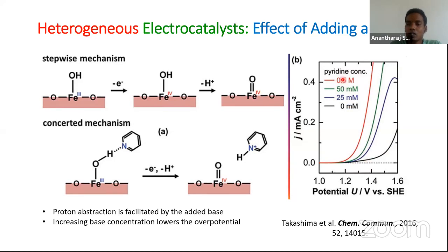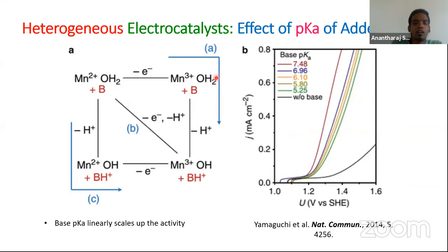And when the base concentration is periodically increased, you can see with increasing base, the activity increases, current increases, and overpotential decreases. So this clearly says that neutral water splitting is not only depending on the catalyst property, it also depends on the added materials and the electrolyte composition, and so many other things. And in a related study by another group of people, they found the pKa of added base. We know that pKa is a metric used in chemical equilibria to predict the acid or base strength. The pKa of base is very important in modulating the OER activity of heterogeneous electrocatalyst.